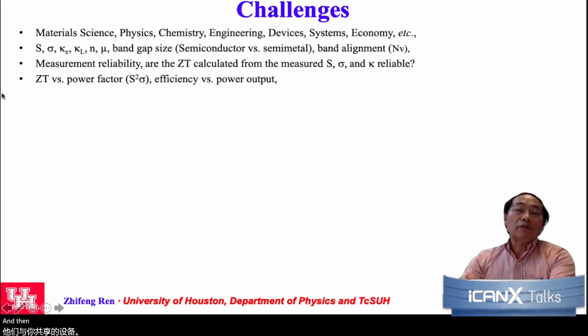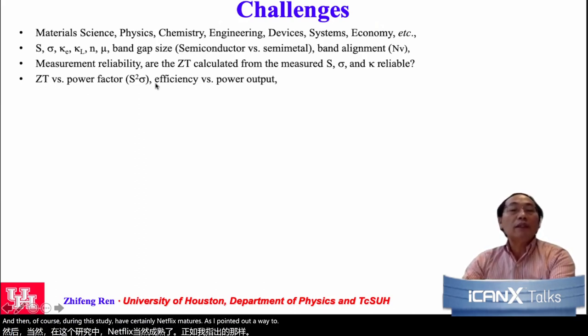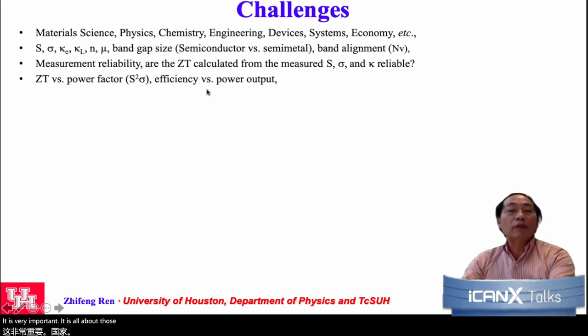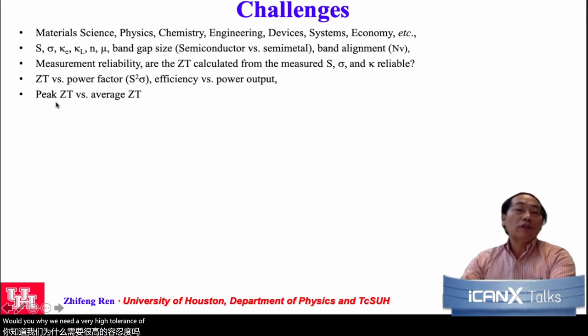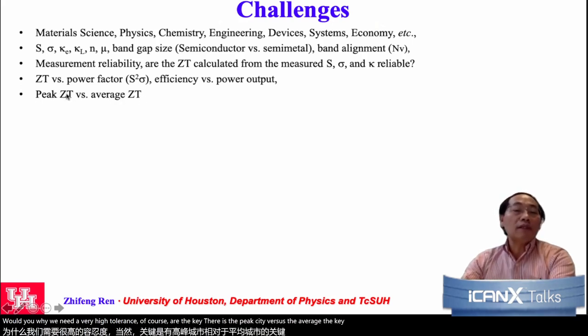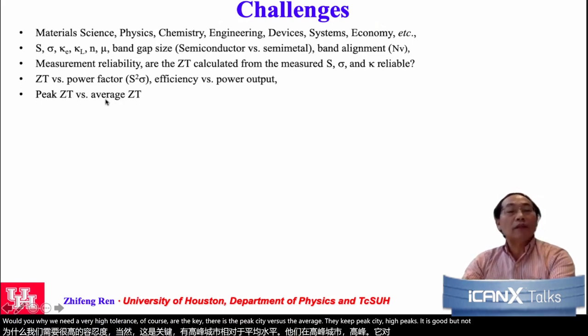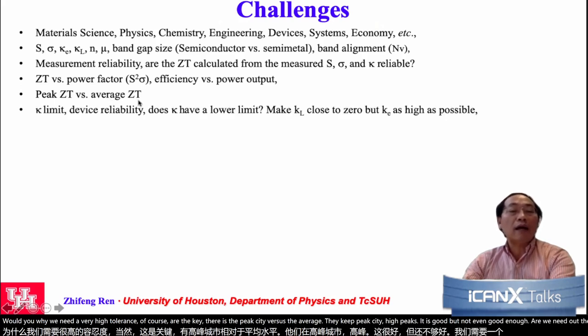And then, of course, during the study of thermoelectric materials, as I pointed out already, ZT is closely related to efficiency, but the power factor is very important, since the power factor is closely related to power output, not the ZT. For any device, we want to have as many watts as possible, which is why we need a very high power factor. Of course, there is the peak ZT versus the average ZT. A high peak ZT is good, but not good enough. We need a very high average ZT.